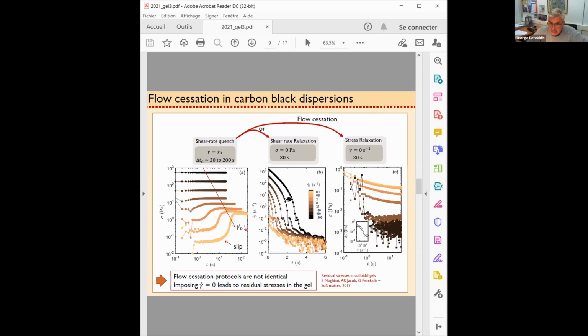But I know, but what I'm saying is that the protocol now is anyway quite mixed, and it is technically impossible to put stress 0 without properly taking into account the inertia of the tool. So the tool will, even if you put stress 0, keep moving, and that would create... I agree. That's basically what we see here in the curve. You see this exponential decay. That's due to the inertia. It's a combined effect of the viscosity of the fluid and inertia.